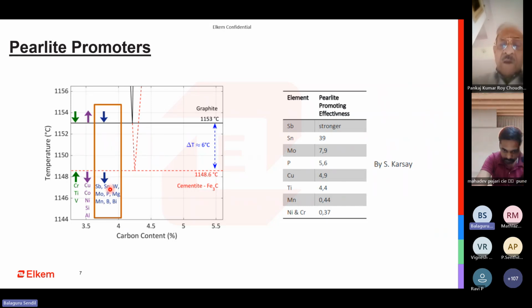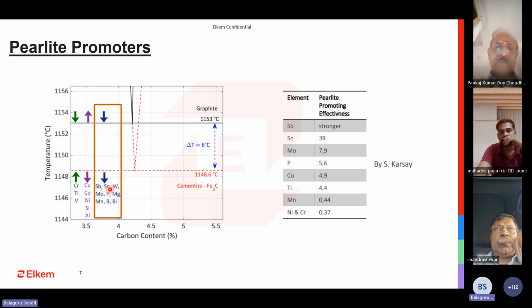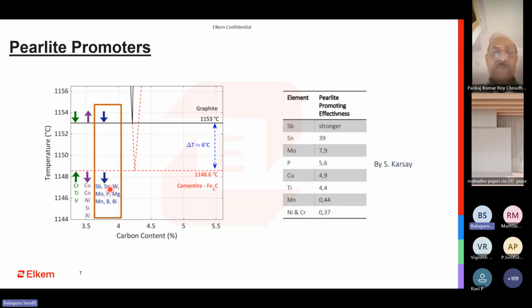So this can also, to some extent, be controlled with our process. The risk of having too much pearlite or less pearlite, with respect to element control and with respect to cooling, at least we have two variables in which we can control it. So the foundrymen typically tend to take out the way which is suitable for them. If they are forced to use a certain type of scrap, then they can play out with the knockout time. So there are two variables at play here, which is in a way better.